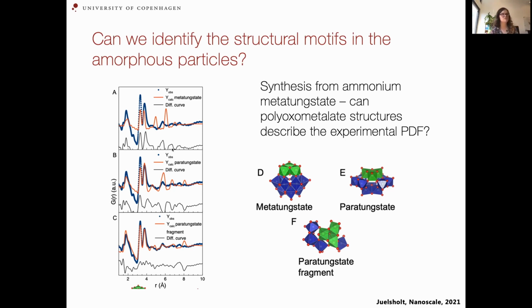So first we tried to fit the PDF with a metatungstate, and that really doesn't go so well. There are definitely peaks that we don't have. But if we consider the paratungstate, which is a different cluster, which we have also worked with before, then we see that at least some of the peaks are there. Now, we don't really believe that we have these large ions in the amorphous material, but we think that the local chemistry of the amorphous particles probably is related to these, because it's about how many different ways you can organize tungsten oxide polyhedra. So what we did was a lot of modeling again, and we cut out these fragments, and we tried a lot of different fragments to see if we have this local structure, whether we can actually fit the PDF from these amorphous nanoparticles.